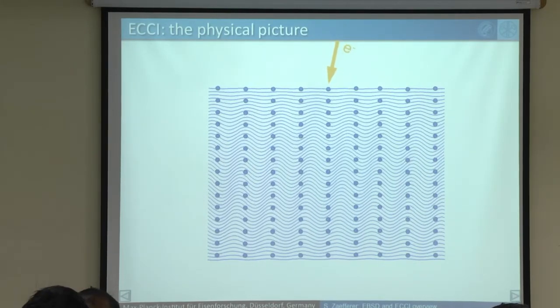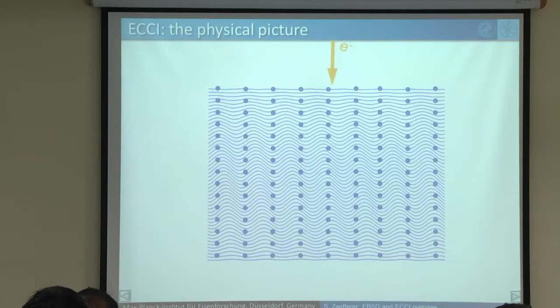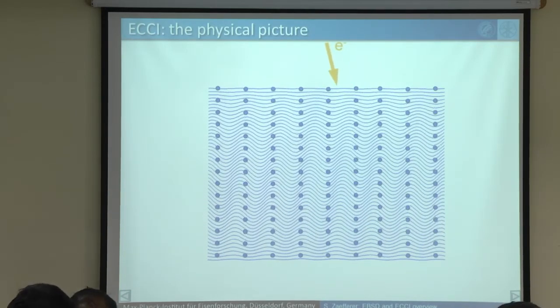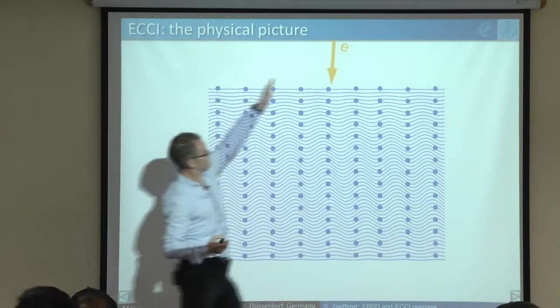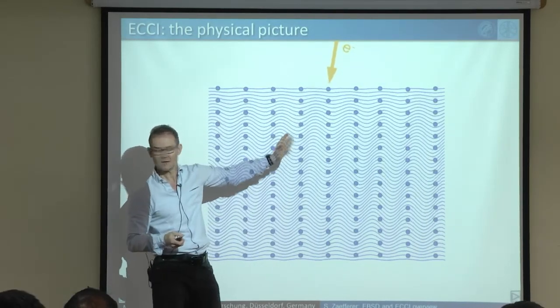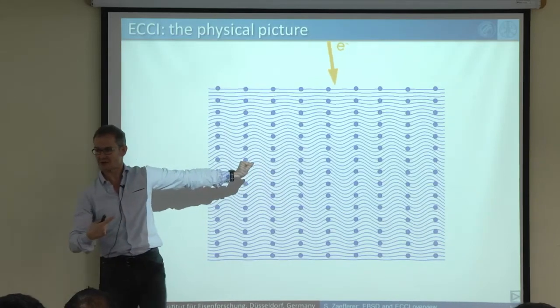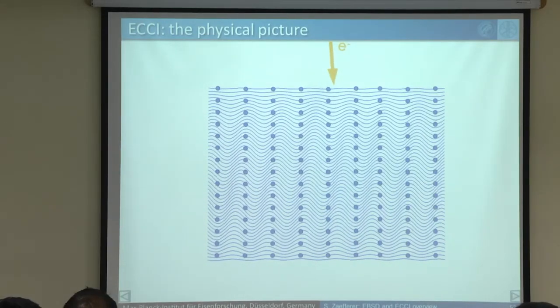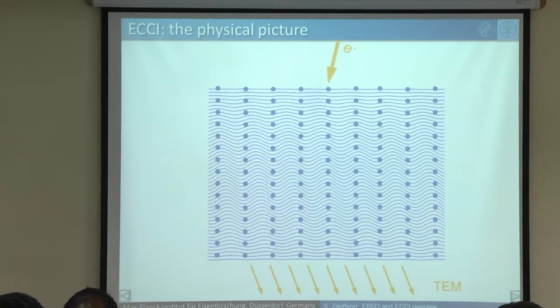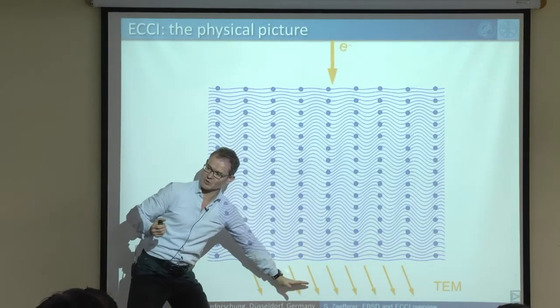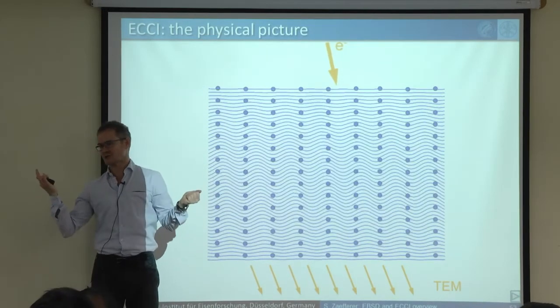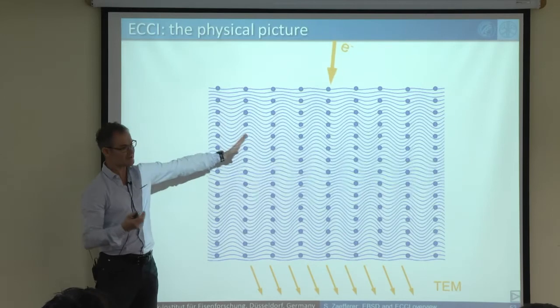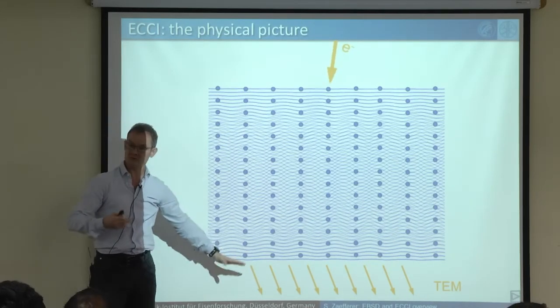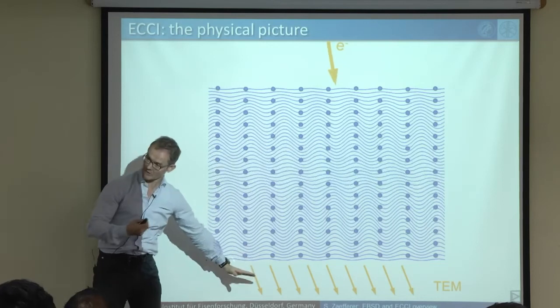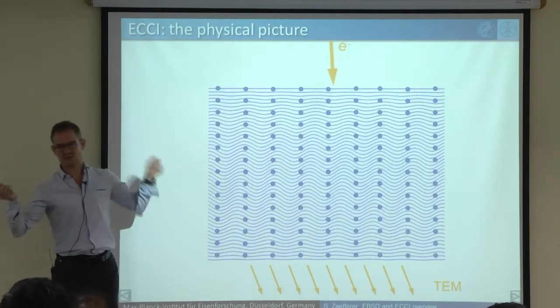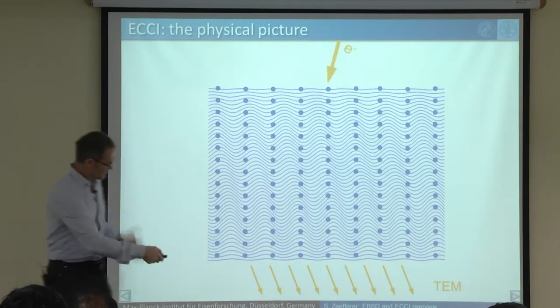Okay, and now you see that this obviously depends on the direction of the primary electron beam with respect to the lattice. And I can tell you already, when the electron beam hits exactly in the Bragg direction, then we see a particular distribution of electrons inside. Good. And in TEM, under certain directions, we would get a resulting electron wave out, and we call this diffraction. When we are in the Bragg angle here, we will see a very strong resulting beam, and we call this two-beam Bragg diffraction. So that's clear, everyone knows.